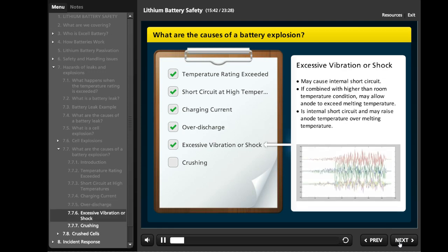Excessively high vibration or shock may cause an internal short circuit, and if combined with higher than room temperature conditions, may allow the anode to exceed its melting temperature. In many cases, this could be due to the separator paper tearing and allowing direct contact between the anode and the cathode. This is an internal short circuit, and it may raise the anode temperature over the melting temperature.